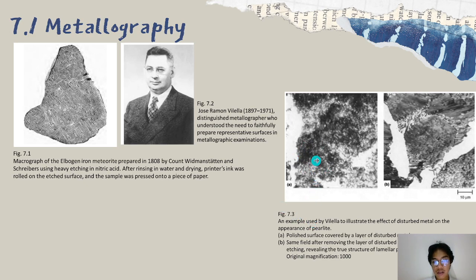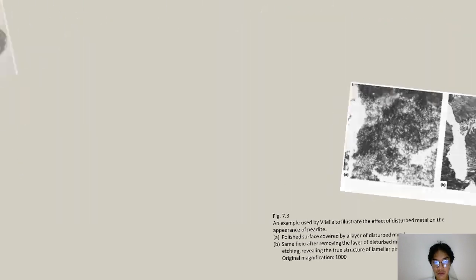In A is a polished surface covered by a layer of disturbed metal. In B is the same field after removing the layer of disturbed metal by alternate polishing and etching, revealing the true structure of lamellar perlite. Etched in picral, original magnification is 1000.